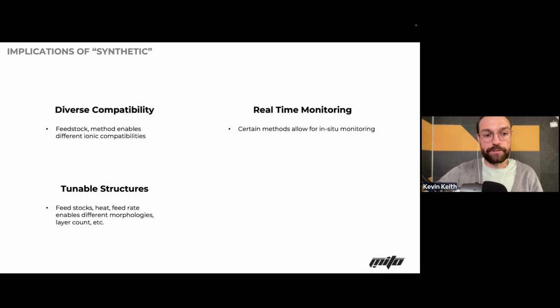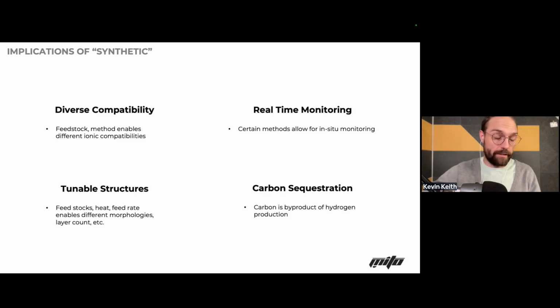Like any production method, you can look at feedstocks and heat. Feed rate enables different morphologies, which have different benefits for composites and lubricants and concrete, layer count, all that fun stuff. And because you're feeding in these hydrocarbons or bio waste, polymers, that type of stuff, you're in a way going through a carbon sequestration. Typically, with hydrogen production, for instance, people put methane through a pyrolysis method. Out the other end comes hydrogen and carbon particles. Depending on their whole setup, again going back to the tunable structures, you have either carbon black, graphene, or even solid carbon. Most of the time, currently, that solid carbon is buried in the ground.